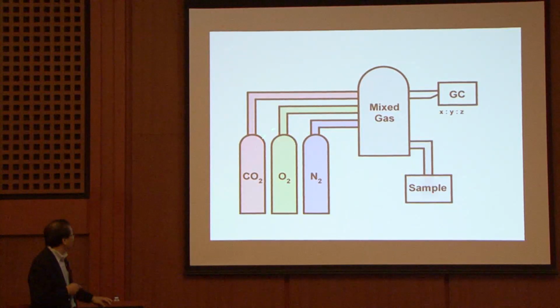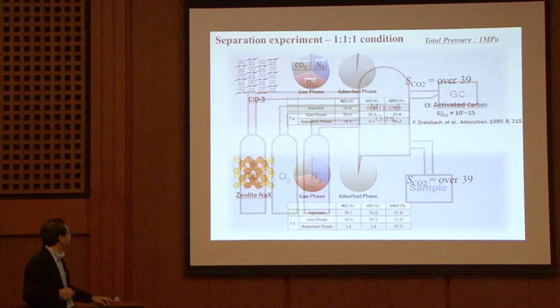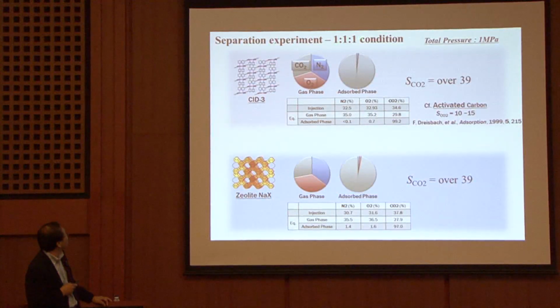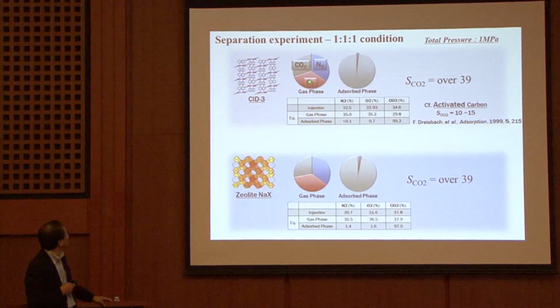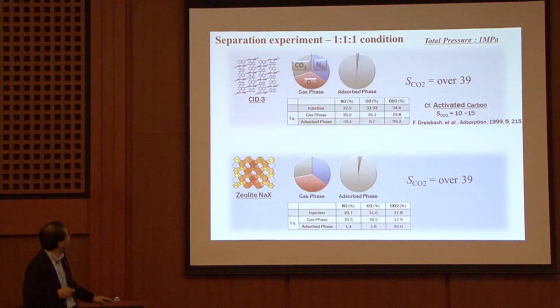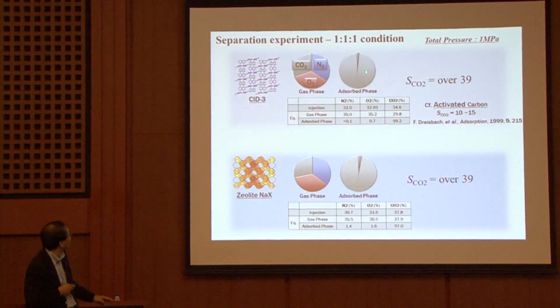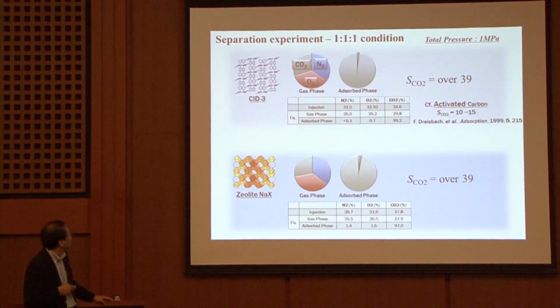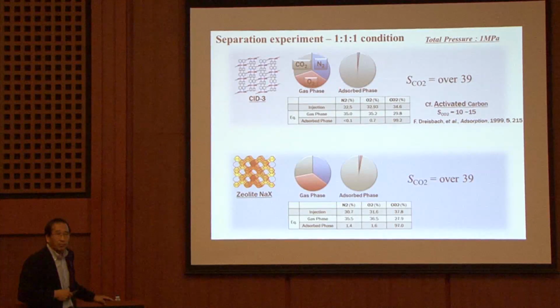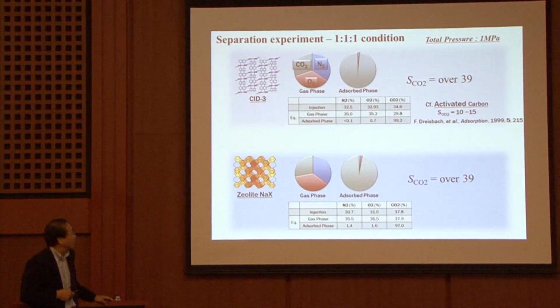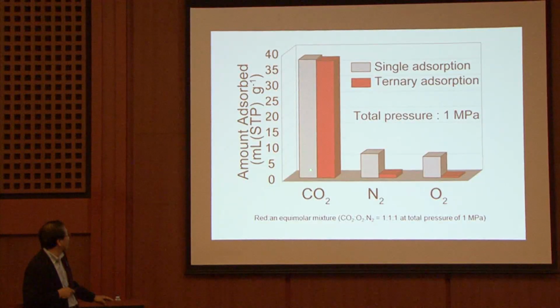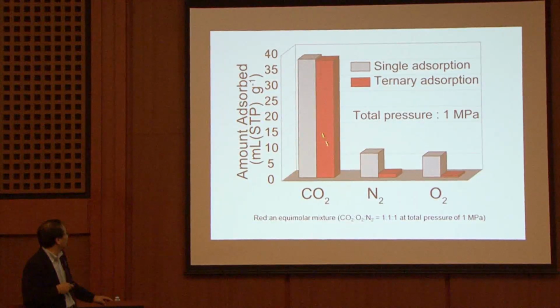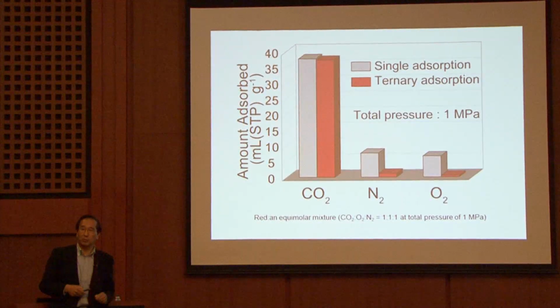Okay, we carried out the mixture of gases. Our compound here, a 1:1:1 mixture. This is the initial mixture ratio, 1:1:1. But in the cavities, only CO2 is adsorbed, 99%. Zeolite also 97%. Selectivity is very close to each other. Why so? Our compound shows the single gas adsorption like this, but in the case of a mixture, CO2 is preferentially adsorbed.